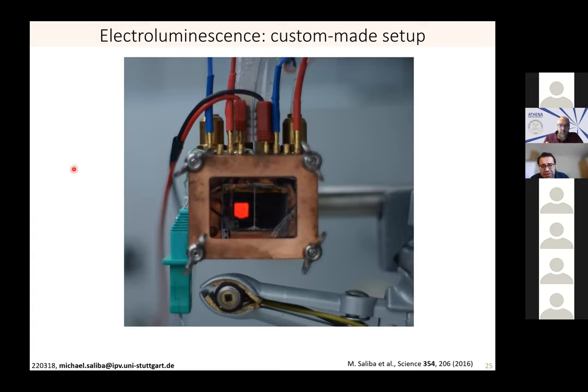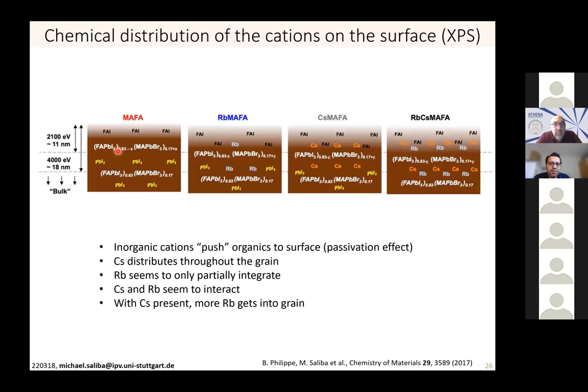And then, of course, the question is, what's the exact role of rubidium? And there are a few stories of it. So it doesn't go into the unit cell, clearly. This has been known for a long time. That's also what we saw from this yellow phase. It never forms a black phase on its own. However, it changes the crystallization process dramatically. And also, it appears to change the way